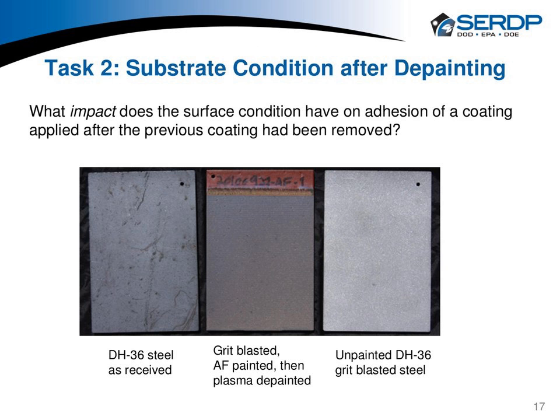The first panel here is as-received steel from the manufacturer, and anyone who's familiar with steel knows that these surfaces have a lot of loosely bound oxides in addition to grease and other types of particles that have to be removed. And that's what effective grit blasting does. One, it removes a lot of those contaminants, and it also imparts a surface profile to the surface that we'll talk a little bit more about as we go on. Well, here's an example of grit blasting, and I think everyone on here can notice that it looks like it's somewhere in between the two.